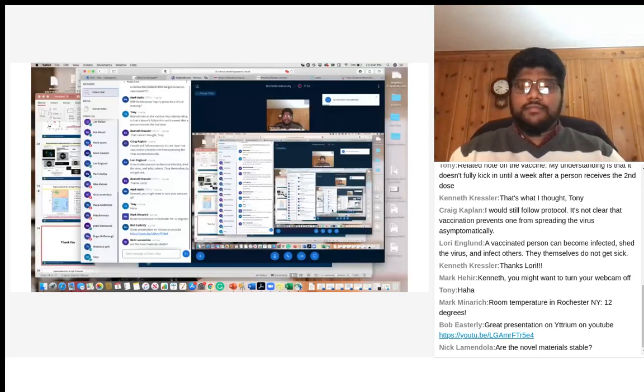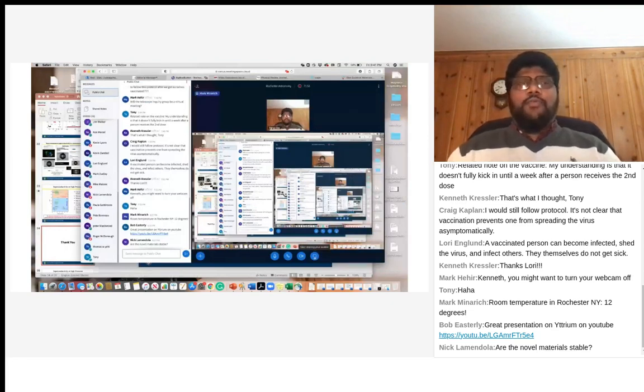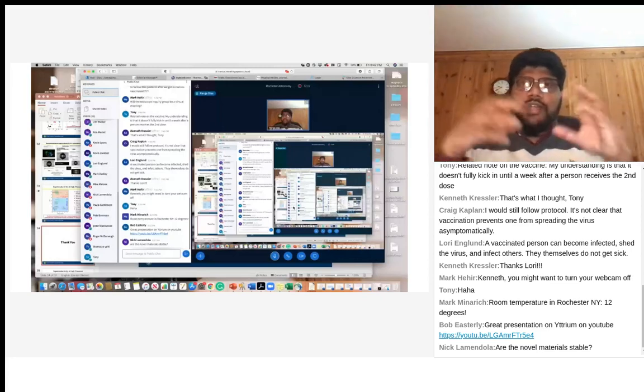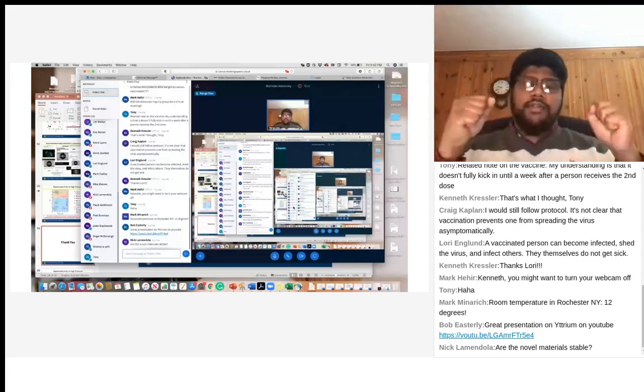Thanks, Ranga. Nick asked the question, are the novel materials stable? We haven't tested that yet. The thing is that when you do a high pressure experiment, you always end up breaking your diamond. Hydrogen is very diffusive. It goes into the diamond and then it cracks the diamond.